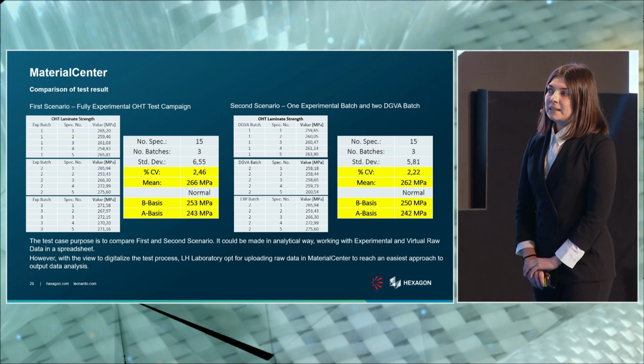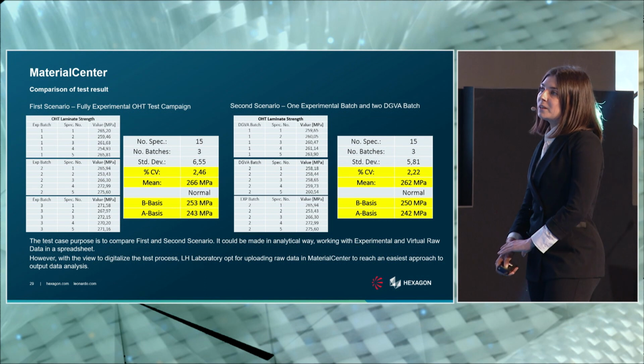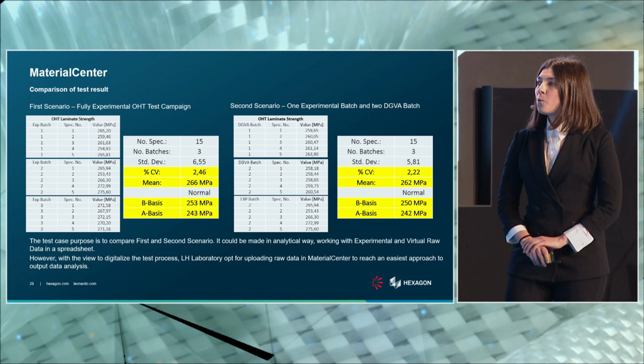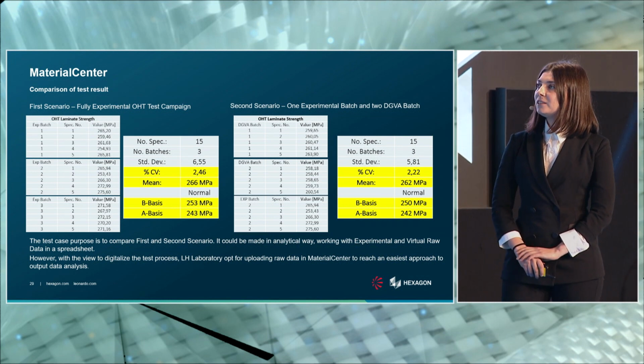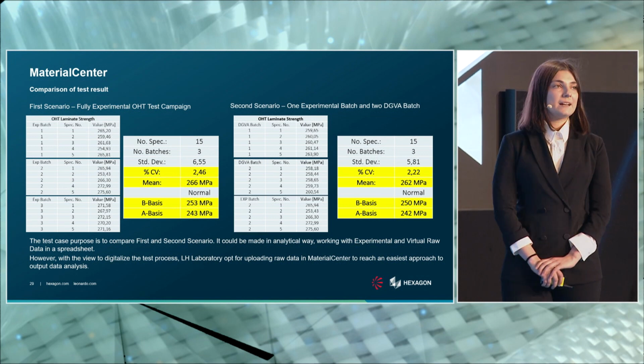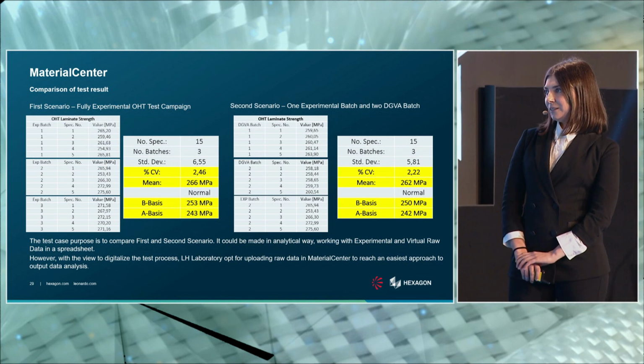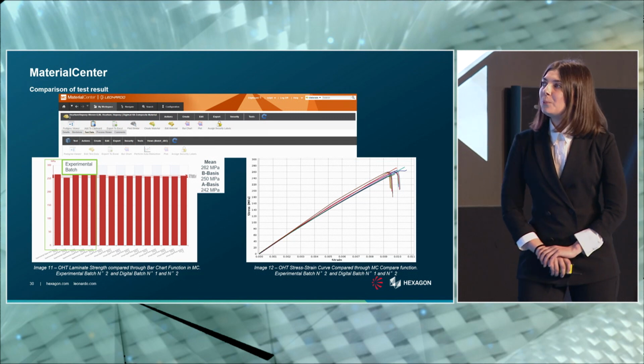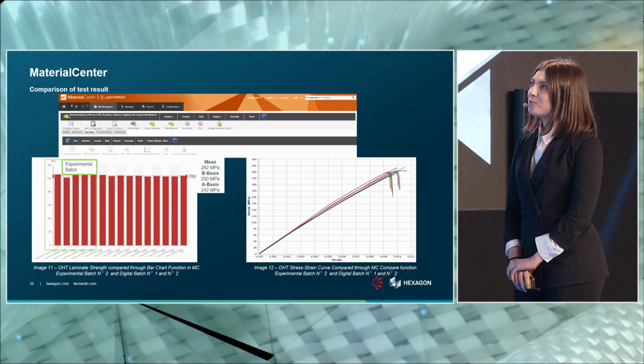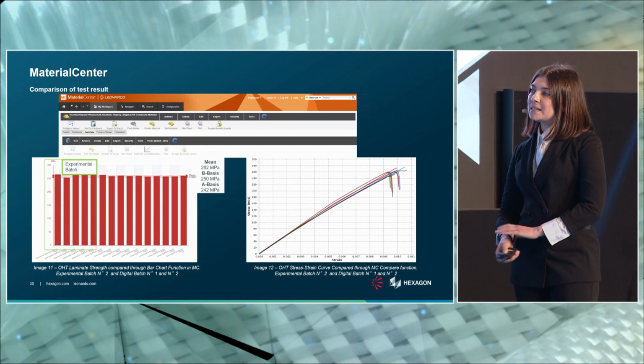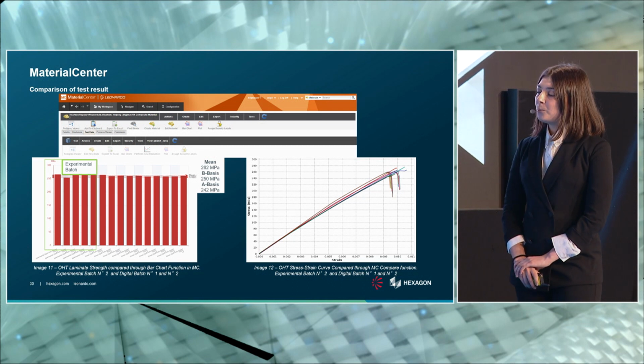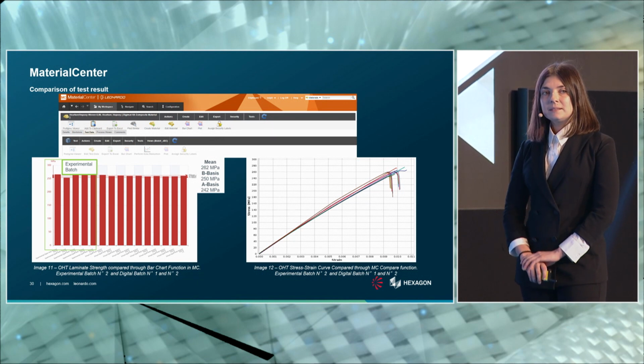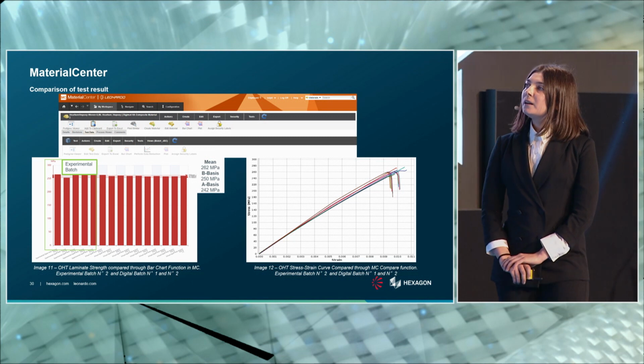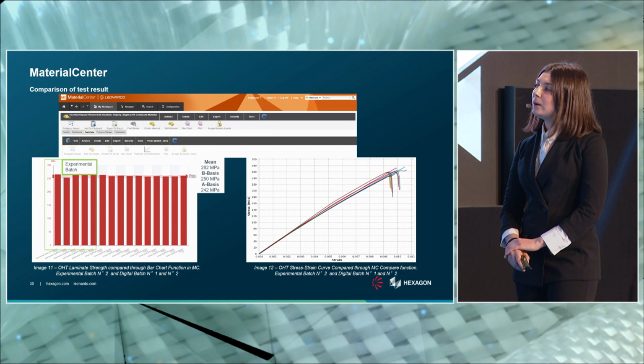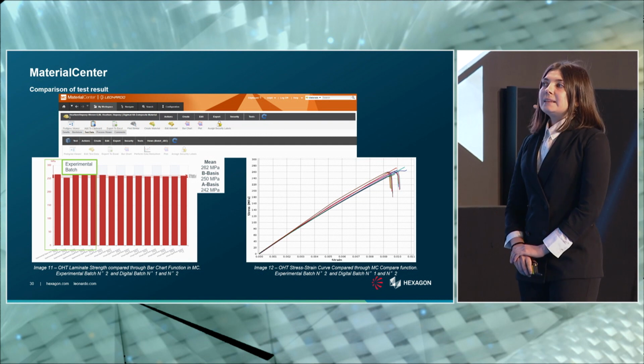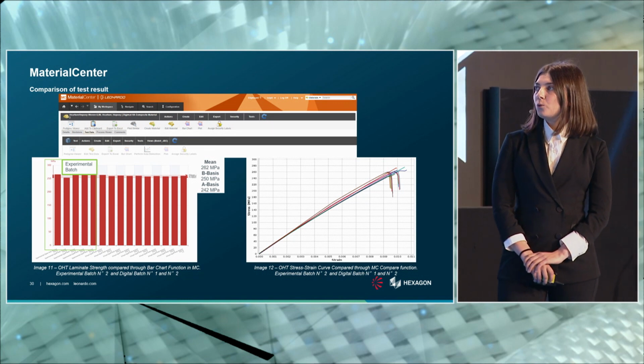And this analysis could be made using a common spreadsheet, but we want to reach material digitalization, and for this we use another Hexagon product, MaterialCenter. In the upper part of the slide, we can see the Leonardo interface of MaterialCenter. And on the left side, we can see the bar chart comparison of 5 experimental coupons for 1 batch and 2 virtual batches with 5 coupons each.